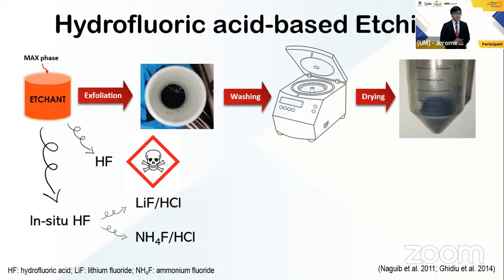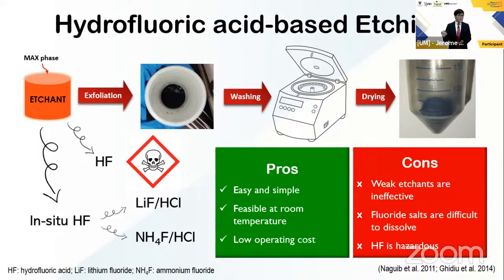This is an extremely easy and primitive method, and it's cheap to run, and it's feasible at room temperature. It all sounds too good to be true until you realize that they suffer from poor etching efficiency, because these in situ HF methods produce hydrofluoric acid at a much lower concentration that is less harsh as an etchant. And this makes the exfoliation of more exotic MXenes, for example, vanadium, molybdenum, and niobium MXenes, much more difficult.